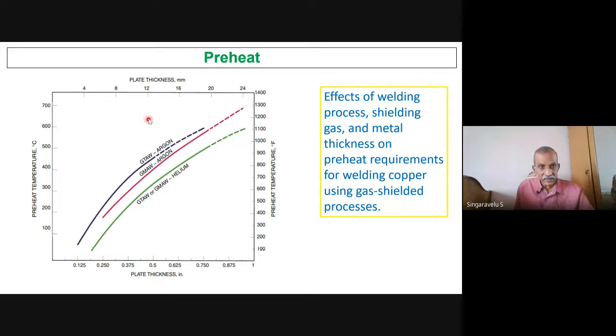For example, if the plate thickness is say 12 mm, right? If you do TIG welding with argon, it's around 425 degrees centigrade, or 450, as your preheating temperature. But the same TIG welding, if you are doing with helium, you can reduce the preheat to 250. The shielding gas has an effect in reducing the preheating temperature. It is not so in steel welding, right? There it is carbon equivalent, thickness and all. With GMAW argon, you can go with a much lower preheating temperature. Okay, that is the effect on preheating. That is how you have to select. If you go with argon MIG welding, what is the preheat? With TIG welding, you have to increase. And the same TIG welding process, if you go with helium, there is a big difference due to the properties of these gases.